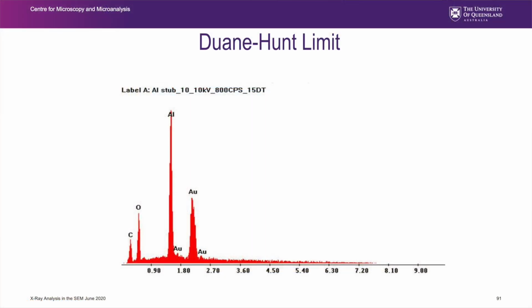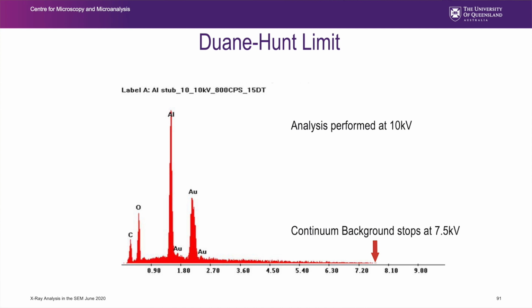A good example of the Duane-Hunt limit. This was done at 10 kV, yet if you look at my continuum background, it stops at somewhere about 7.5 kV, 7.5 to 8 kV. So that shows me I had over 2,000 volts of subsurface charging. So that's a good example of the Duane-Hunt limit. The continuum stops there. This specimen was charging up badly.